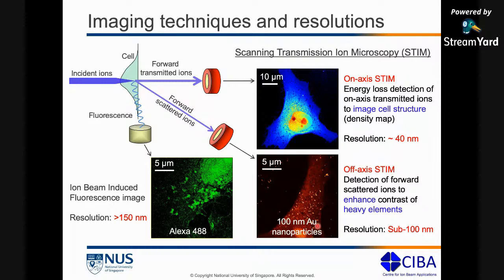So while an off-axis STIM image will preserve your detector and give you elemental contrast, you lose out on the resolution. But for an on-axis STIM image, you get good resolution, but then you have a higher chance of damaging your detector. That doesn't mean that we don't do on-axis STIM. We do on-axis STIM imaging, but we keep it to a bare minimum. If you want a good high resolution image, you will just take one image of the sample using on-axis STIM, and then the same detector, we switch it to an off-axis mode, and then we start collecting forward scattered ions in the off-axis mode, where we then get this elemental contrast as well.